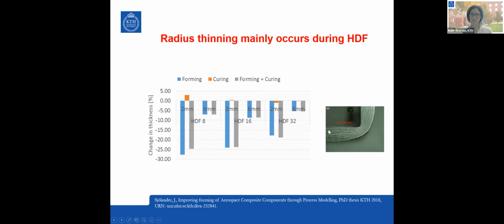Looking at one of the pictures, this is a really bad picture from a high pressure forming experiment. But if you start looking into different thickness of the layers here, you find that where you have the fibers going in this direction, of course the thickness has to remain more or less, because it's difficult to move these fibers, while the other layers where you have fibers going into the picture, so to speak, they had a tendency to move during the forming operation. And this movement, or squeeze flow, of layers, of course, is influenced by the temperature that you form at.